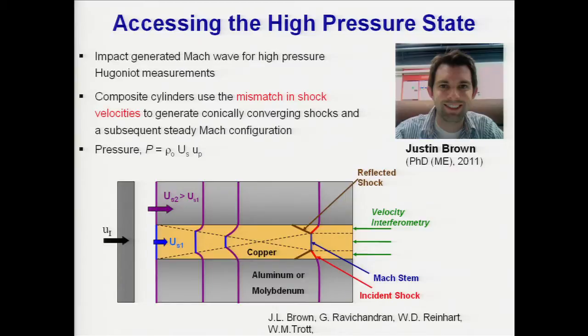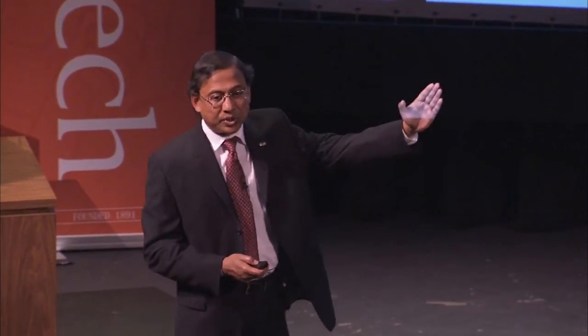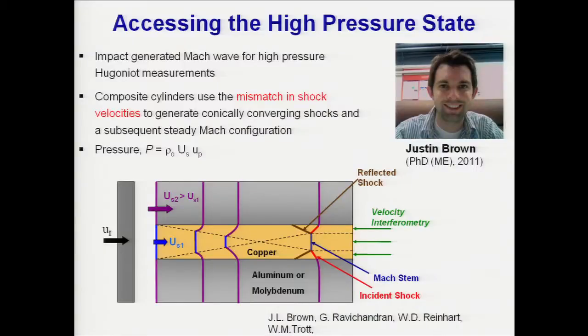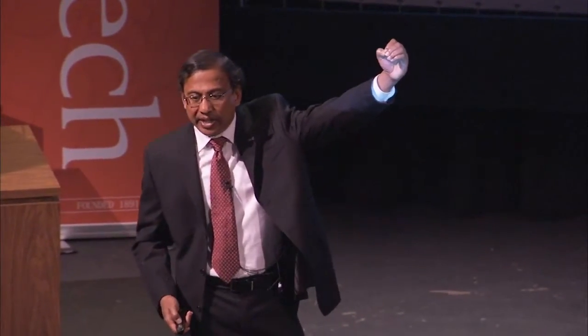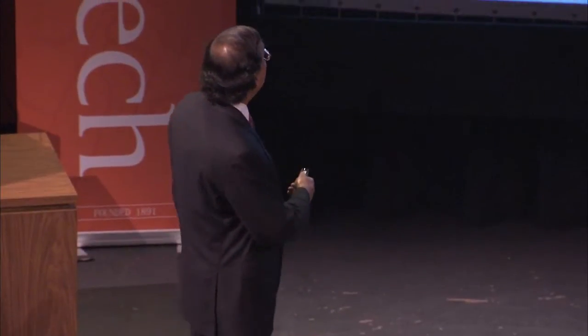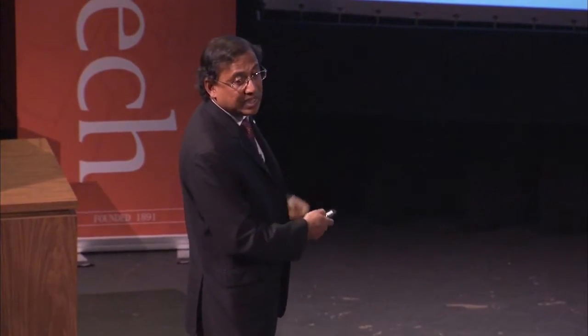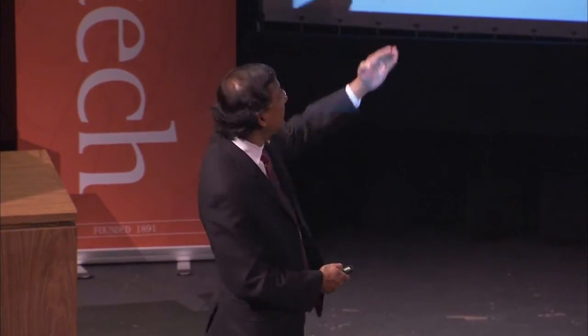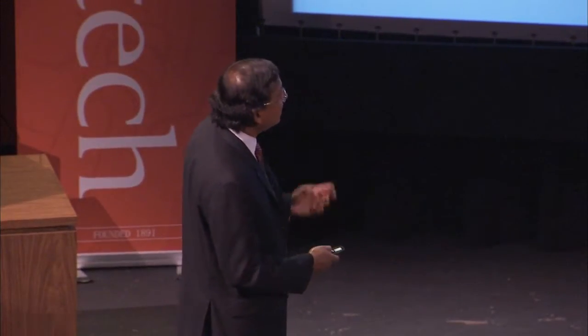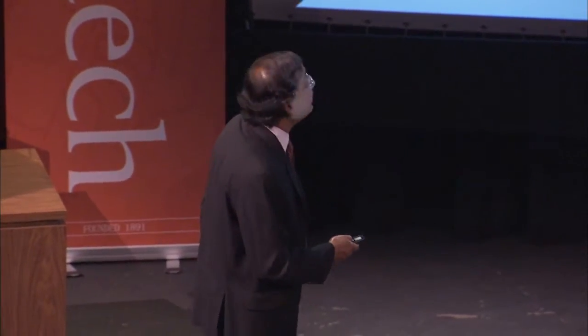Then as it expands, it creates the so-called Mach stem, similar to the Mach waves which we saw when an aircraft flies supersonically. This creates a high-pressure region here, and this Mach stem is propagating at the shockwave speed of the outer material. So artificially, I have increased the shockwave speed in the material, even though my impact velocity is limited. This way, I can achieve higher pressures, even though my impact speed is limited. So this is the simple idea which Justin Brown used.